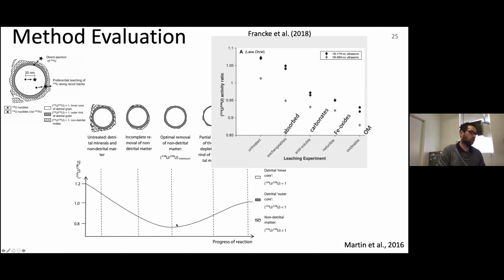Because while you lose the uranium-234 from the grain into the surrounding pore water, any material that is formed from said pore water will take up this activity ratio above 1. So organic matter, calcite, carbonates, iron oxides, any secondary matter usually is characterized by activity ratios much, much higher than 1. So by sequential leaching, we remove all this authigenic matter from the bulk sediment composition, and we should, with each treatment step, see this decrease in our activity ratios.